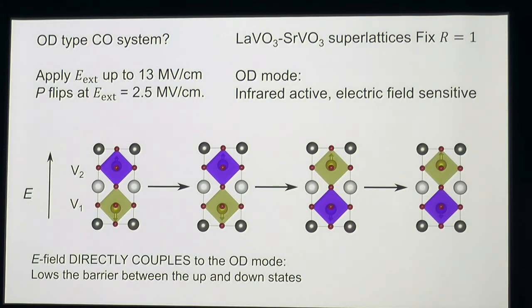But how about the other type, the off-center displacement type? Here, we use a fictitious example, which is also such a superlattice. But we fix R equal to 1, which means we artificially remove the polyhedral breathing character. We apply an electric field, and at each electric field, we fix the R value. We indeed observe a polarization flipping at an electric field equal to 2.5 MV per centimeter, which can be achieved in experiments. The mechanism is that such a lattice mode is directly coupled to the electric field, and the electric field can lower the energy barrier between the up and down states and induce the polarization flipping.